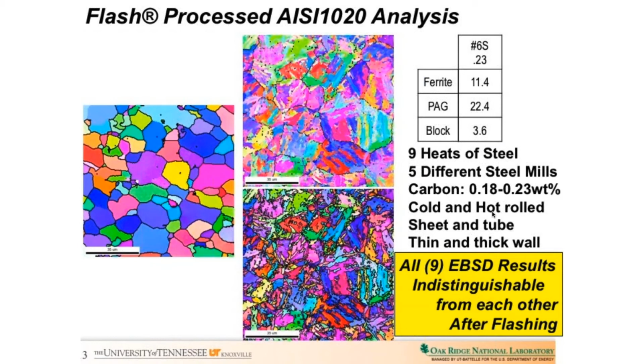Some was hot rolled, some was cold rolled, some was sheet that was heated and cooled from both sides, while others was tubing that was only heated and quenched from the outside of the tube, just because that's where your apparatus can attack the steel from. And then we also did thin and thick wall. Now, what was interesting is prior to flash processing, you could take those 9 heats of steel, do EBSD and look at everything microscopically, and you could put them into their own discrete bin so that if somebody randomly grabbed a piece and handed it to you, you would be able to analyze it and put it in its own bin.